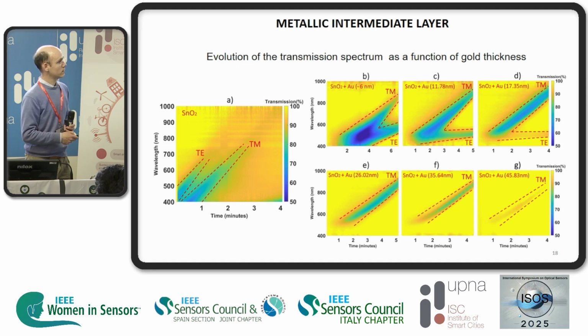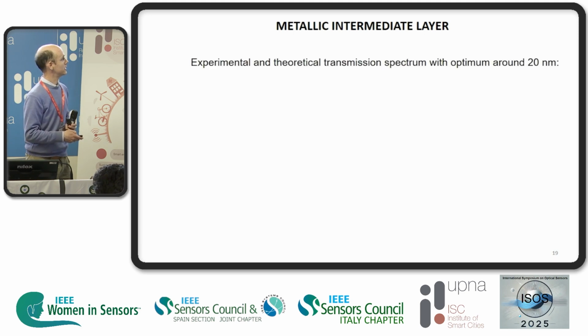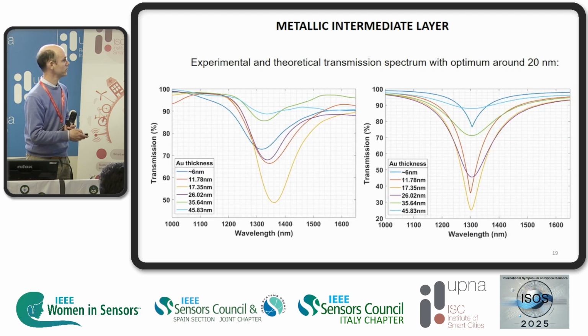And with thicker gold layers, we observe that the TE band fades and the TM also, but for a thicker coating. So what is the most interesting part in this metallic intermediate layer? Here I show experimental and theoretical transmission spectrum with an optimum around 20 nanometer, and you can see here that the deepest band is here, similar to the simulation results.